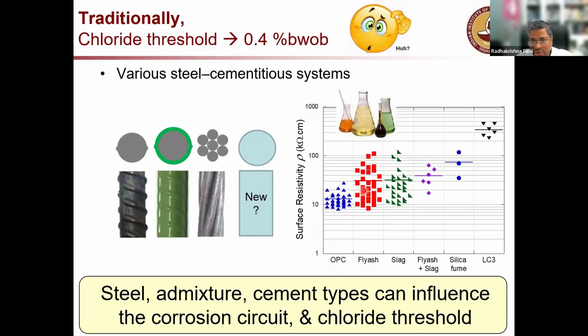Or in other words, the resistivity of the concrete has significantly increased with the use of fly ash, low water binder ratio, and superplasticizers. So if you mix the concrete or come up with a proper mix design where you maximize or optimize the use of supplementary cementitious materials, superplasticizers, etc., you can really get a highly resistive concrete, which will help in resisting the penetration of chlorides, moisture, oxygen, etc. into the concrete, which eventually helps us in building durable concrete structures.